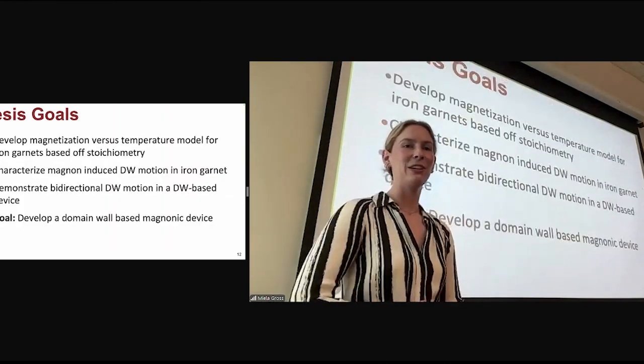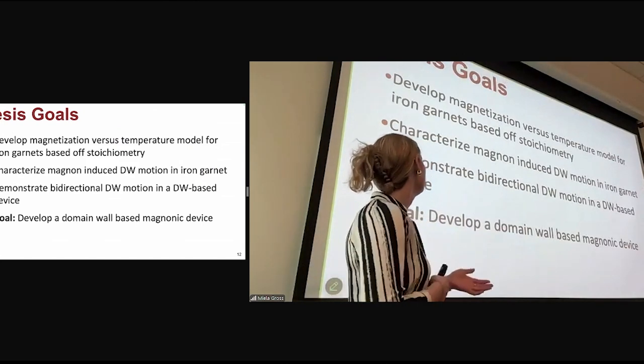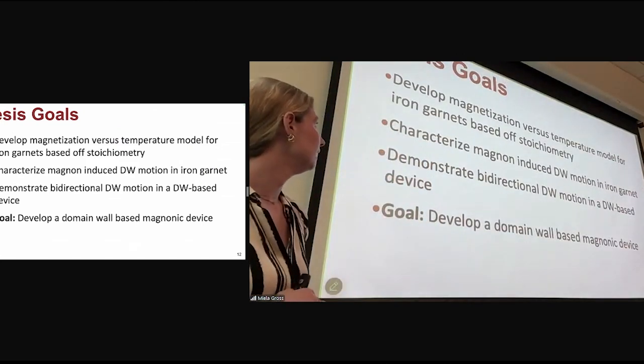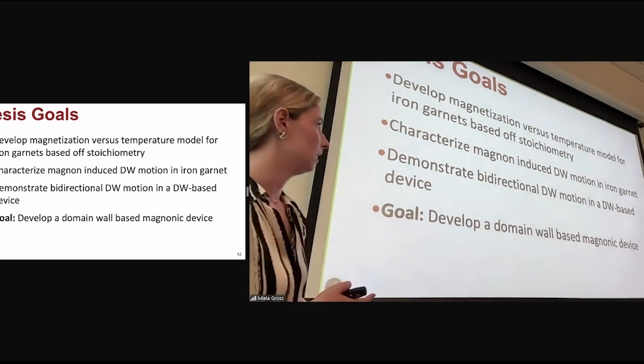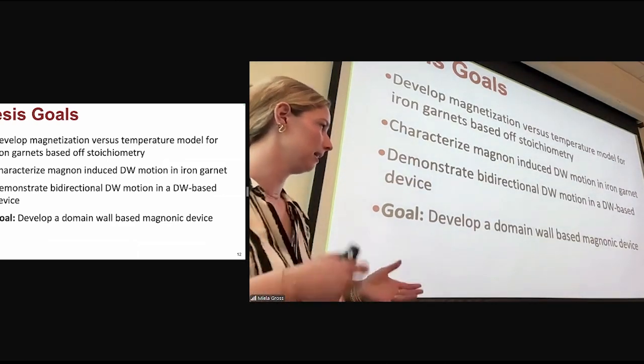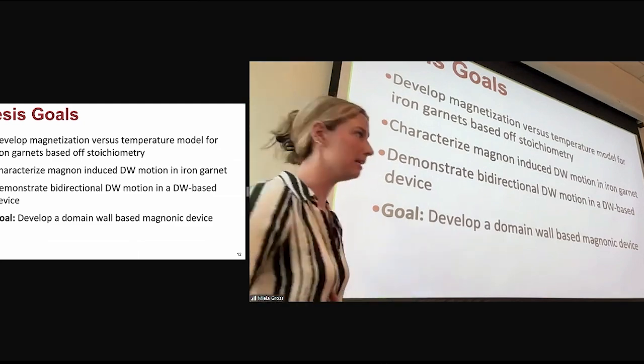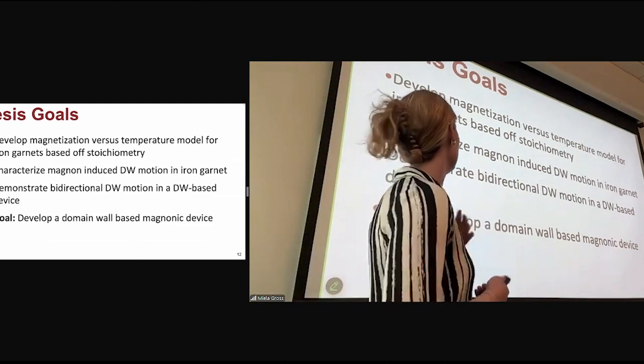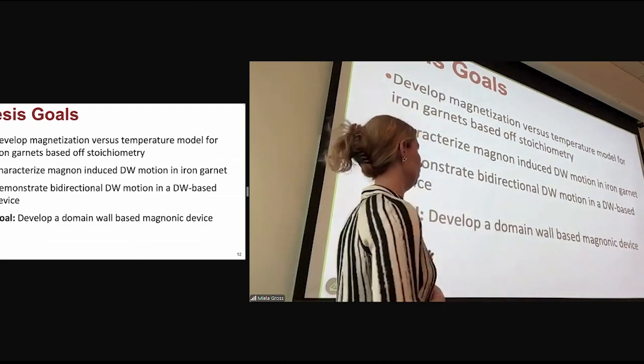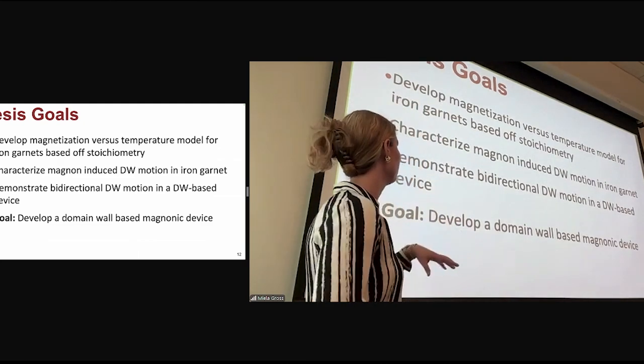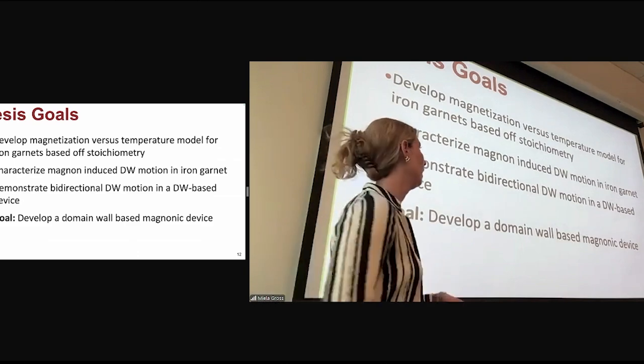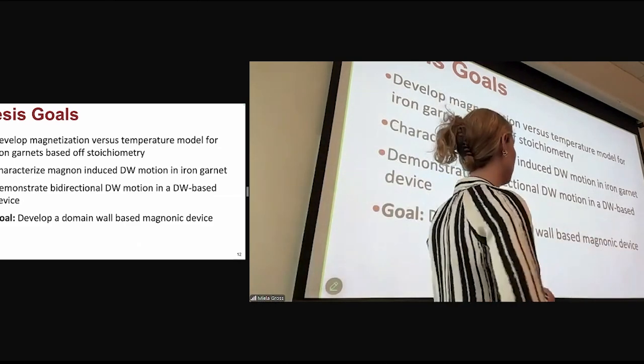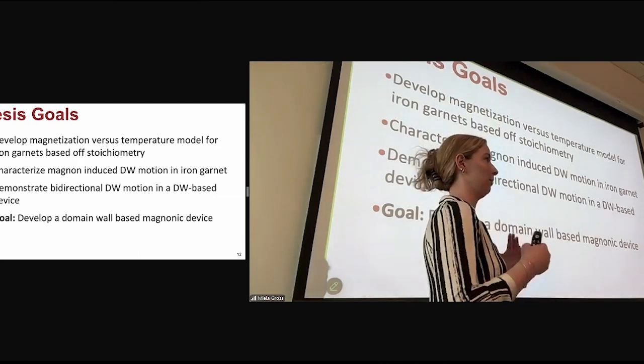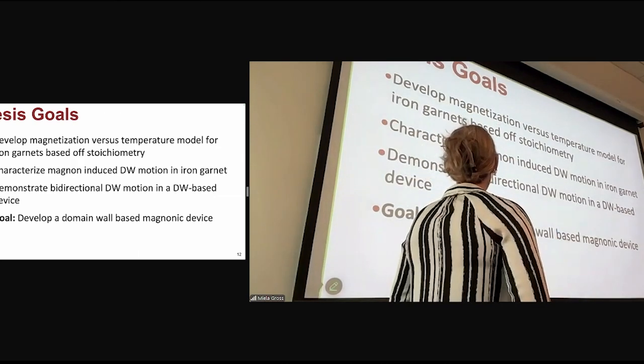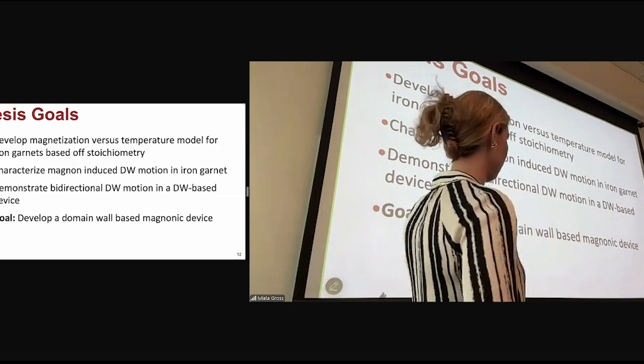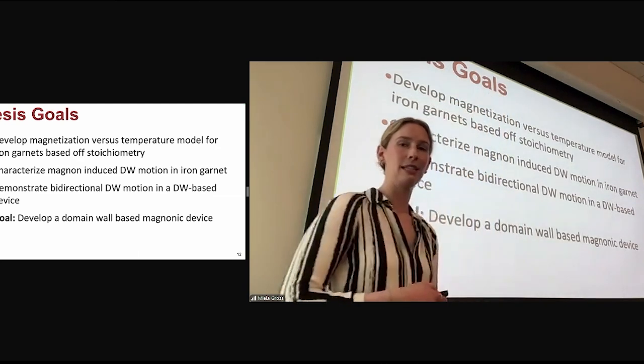Okay, so my thesis goals. My goal here is to show you how I study the different properties of garnet, magnons, and domain walls in developing a write mechanism for a domain wall-based magnonic device. Firstly, I dive into studying iron garnets, specifically developing a model to look at the magnetization as a function of temperature for garnets based off their stoichiometry. I then study the interaction between magnons and domain walls in iron garnet, showing spin wave induced domain wall motion. And lastly, I use that to demonstrate bidirectional domain wall motion in that domain wall based device.